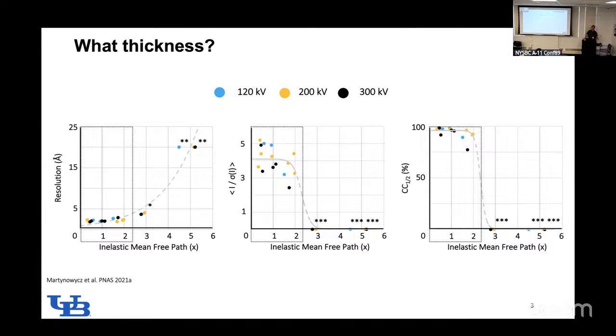I have an aside here, which is my cryo-EM rant about physics. If you've heard of Beer's law and you know how crystallography works, the reason for ion beam milled crystals where we don't want them as thin as possible is you're up against 2 facts. One is as the crystal grows thicker, you're amplifying your signal. And as it grows thicker, you're also losing signal from Beer's law, from the exponential decay. So we end up with something called a vineyard peak, which lo and behold peaks at 1 times the inelastic mean free path.